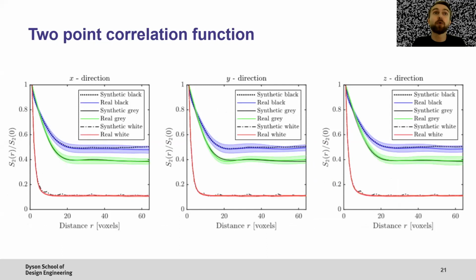Here's the 2-point correlation function. It's a function that says, go to a point in your microstructure, do this for every point, and as a function of distance away from where you currently are, count basically how many of the ones in that particular spherical radius are the same phase as you. So it's this correlation between what you are locally and what everyone else is as a function of distance. And this tells you a lot about the nature of microstructure.